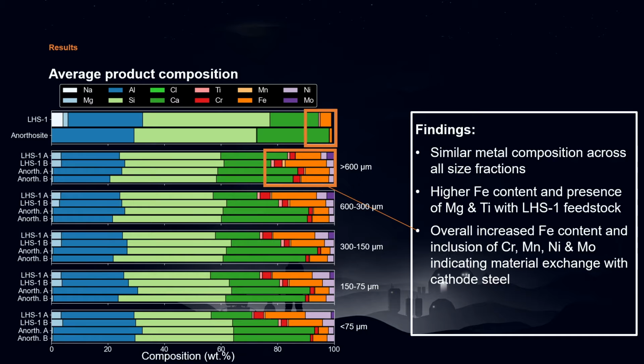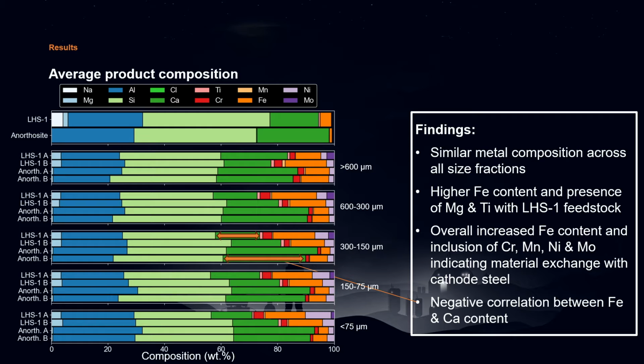Then, if we look at the overall iron present, it is in all cases greater than what we have in the feedstock, and we can also see some exogenous elements appear. For example, we have chromium, manganese, nickel, etc. That indicates that we have some contamination that comes from the cathode, which is stainless steel. So it also shows us that there's still some progress to be made in terms of materials for the reactor. And then finally, this is a bit clearer in complementary analysis that is not discussed here today, but there is a negative correlation between the presence of iron and the presence of calcium in the product we're obtaining. So where you have a lot of calcium, you tend to have less iron, and vice versa.